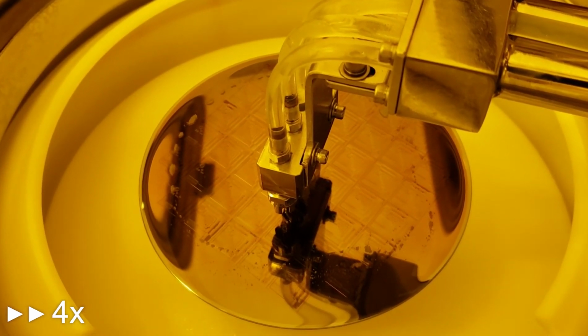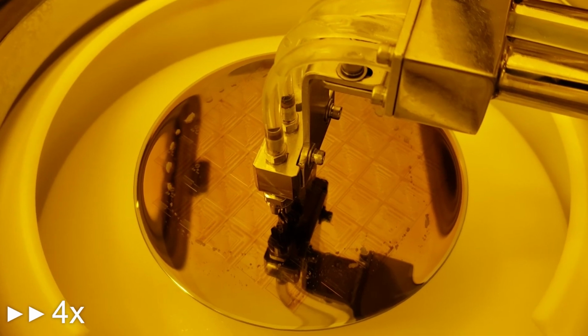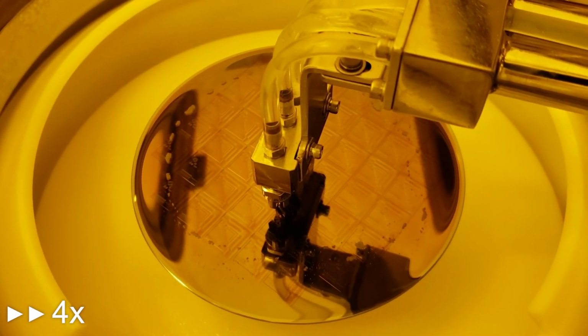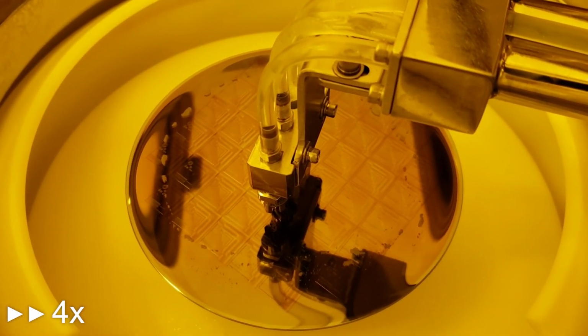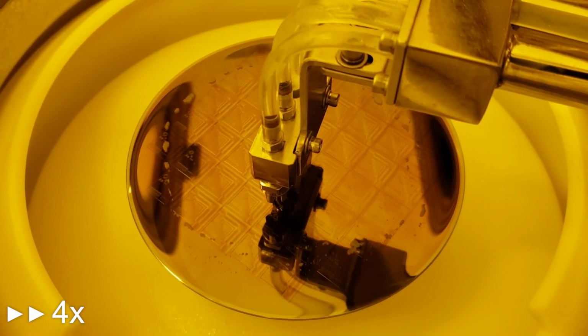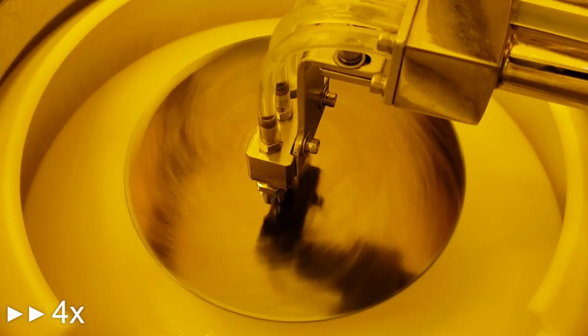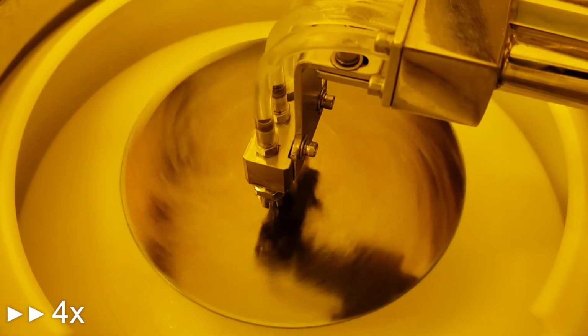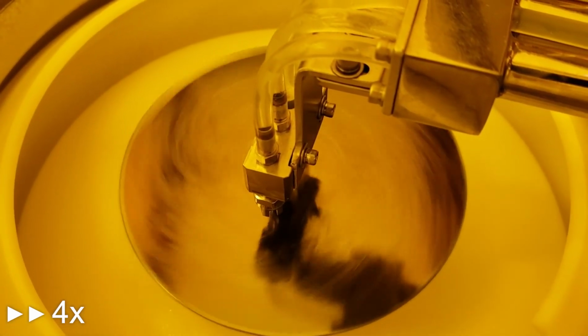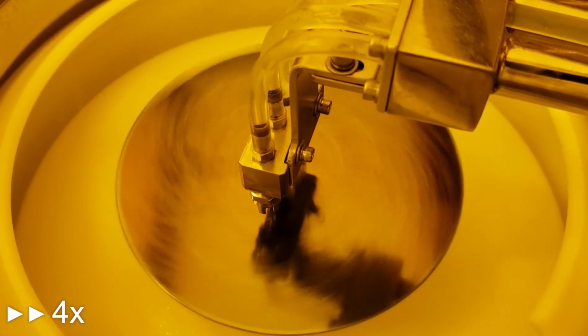The time should be long enough to completely dissolve the soluble photoresist, but not too long, or the pattern may become overdeveloped. After the puddle step, the wafer is spun and rinsed with water to remove all the developer. Lastly, the wafer is spun dry.